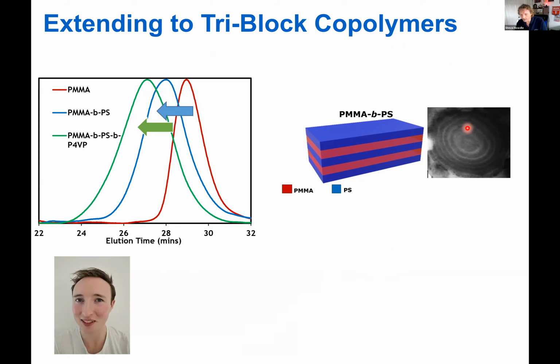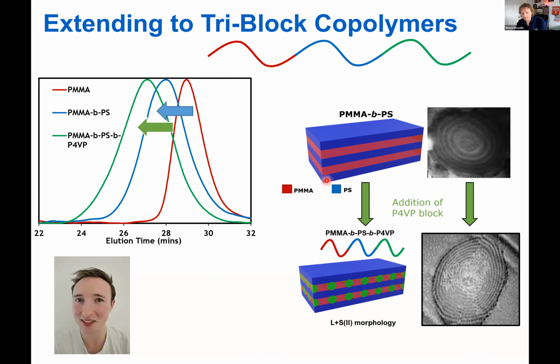Here's the electron microscopy image that proves it. Then when you add in the third block and grow it onto that, the vinyl pyridine only has one place to go, and it has to go into the polymethyl methacrylate, which it also doesn't like, and it phase separates again. We get this sort of spherical arrangement inside of the lamella. And when we look inside the particle, we'll see some really quite unique structures.